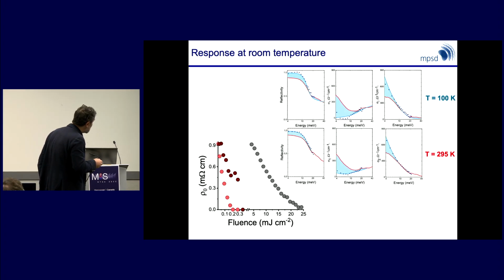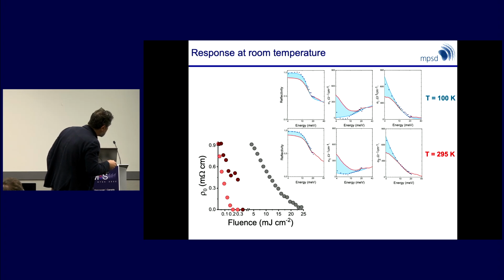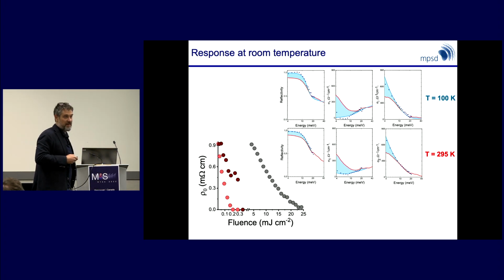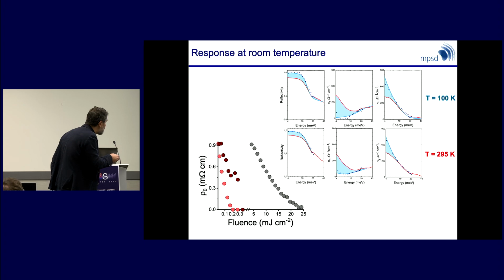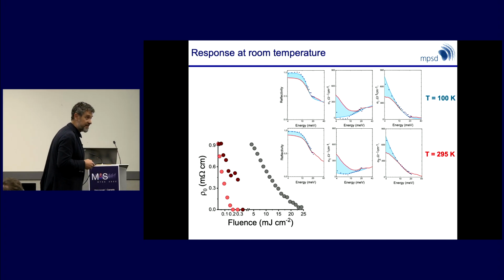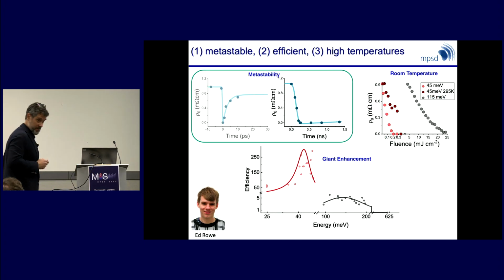Again, you can see that the extracted optical properties at 295, say at room temperature, in the photoinduced state are in the same ballpark as what you fitted for low temperature. So the gap is a little dirtier. Sigma 2 doesn't diverge quite as much, but it's still a very suggestive transient response. And so this was part number 2.